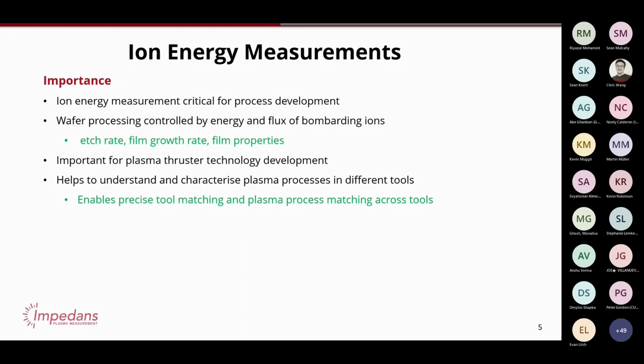In other words, what measuring ions allows you to do is to really understand and characterize what the plasma process is doing to your substrate. Because it's such a direct measurement, it really enables precise tool matching. You can make sure that what the wafer sees in tool A is the same as tool B or tool C or the different modules, and also for process transfer between tools. So if you develop your process on one tool and you buy a new tool set and you want to run the same recipe there, are you going to get the same results? This gives you direct visibility on that.